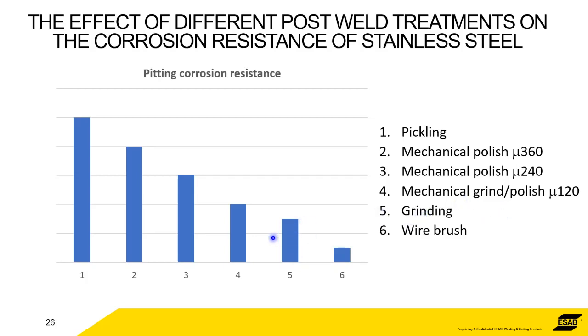When you start to polish, you can see the difference that it has between the various grit sizes from 120 up to 360. So at 360, you've got twice the pitting corrosion resistance. The effect of doing a polish with a grit of 360 is twice as good as the effect of doing a grind and polish at 120 grit. And then the best of all that we recommend would be pickling. That's the best of all. That's going to give you the best results. It's going to return basically the properties of the base metal.